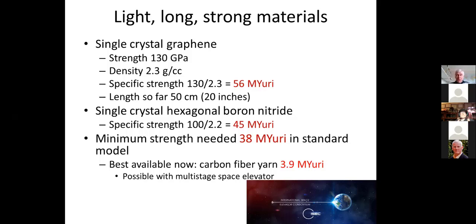The minimum strength we need, as I mentioned, calculated by Ben Shelef, is 38 MYuri in what I call the standard model. That is the model that we usually talk about for the space elevator. The best available commercially now is carbon fiber yarn, which comes in at about 1/10 of what we need. It is possible to use that with a multi-stage space elevator, although as I'll explain, I prefer something in between.